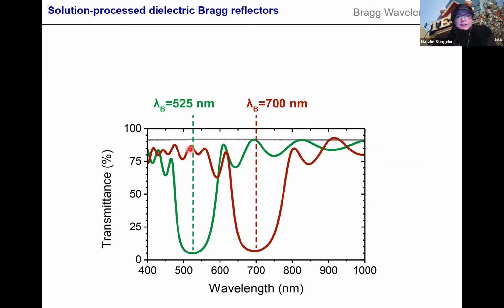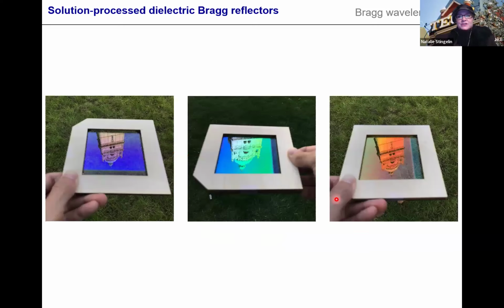And if you have thinner or thicker layers, we reflect green or red, and that's shown here. This was still work from Imperial College, because this is the reflection of the Imperial College tower onto our mirrors. And you also see already the size of those mirrors—they're pretty big.